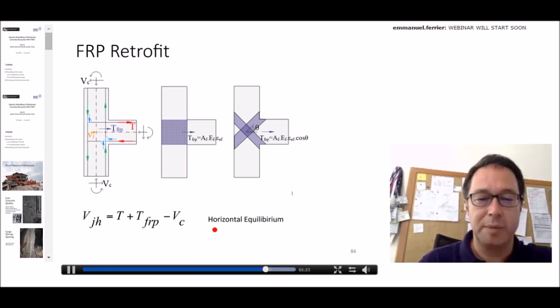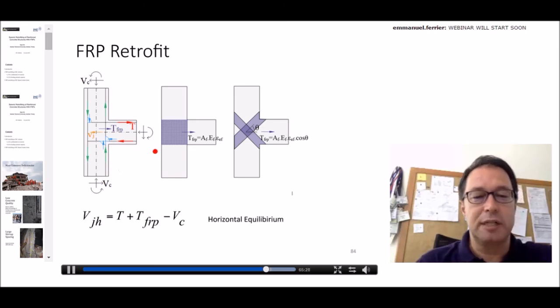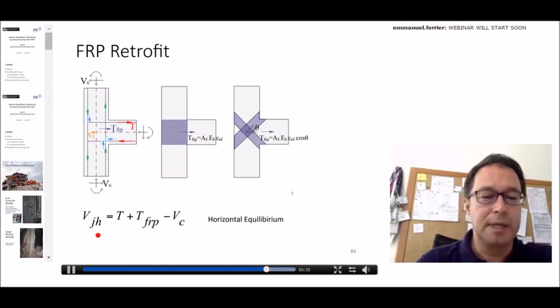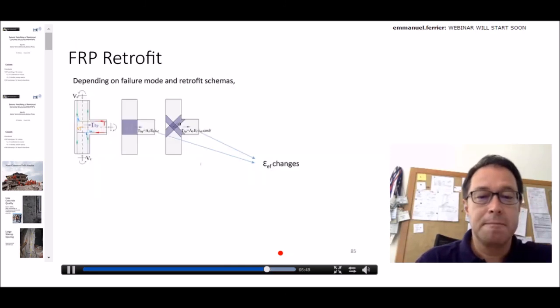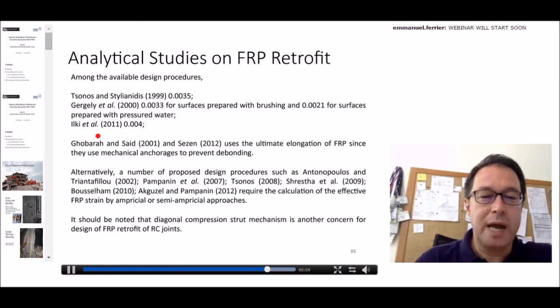So with just a few slides, as also mentioned in the Italian code and several different papers, we could determine the strength of FRP retrofitted joints by making use of simply the horizontal equilibrium equation. But the issue is when the debonding could occur, or what effective FRP strain should be taken into account, because it changes according to application types. For that, different researchers have recommended different values. And here's the value that we could obtain based on the tests shown here.